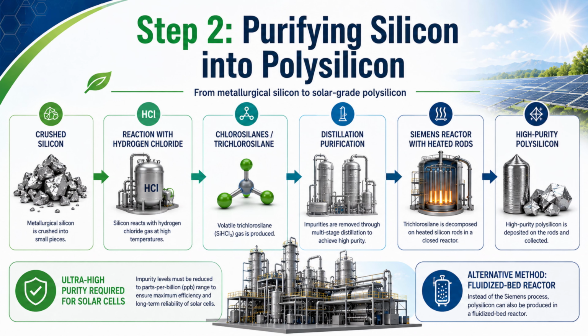One common purification method is the Siemens process. In this method, purified trichlorosilane gas enters a reactor containing heated silicon rods. The gas decomposes on the hot rods, and ultra-pure silicon deposits onto them. Over time, the rods grow into thick, high-purity polysilicon structures. There's also another method called the fluidized bed reactor process, where polysilicon can be produced as small granules instead of large rods. Both methods aim for the same goal, to create silicon clean enough for efficient and reliable solar cells.